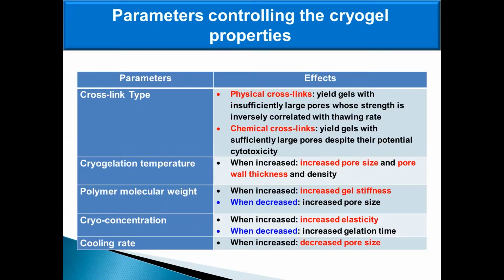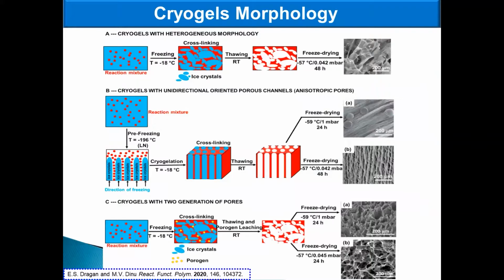The cryogel's properties can be easily tuned by the synthesis conditions. For instance, the pore sizes, the pore wall thickness, as well as the gel stiffness and elasticity could be adjusted by increasing or decreasing the cryogelation temperature, polymer molecular weight, or cooling rate. In addition, the pore morphology could be controlled by combining the cryogelation with an interpenetrating polymer network approach or a porogen leaching strategy. Thus, chitosan-based composite cryogels with heterogeneous morphology or lamellar structures or two generations of pores can be easily prepared.